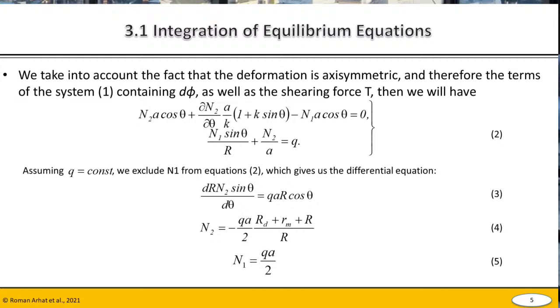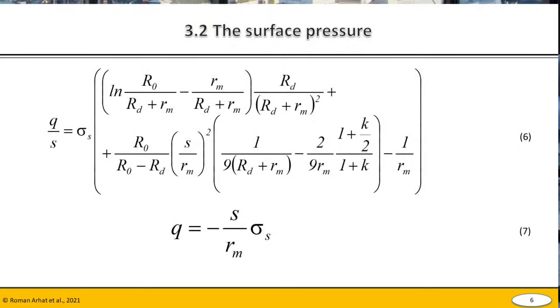Then the surface load is given by equation number 7 at the slide 7. Slide 6, sorry. Slide 6. Thus, an expression has been developed for calculating the surface contact pressure during the drawing down of a cylindrical workpiece, which makes it possible to take friction stresses into account at the rounded radius of the die body, and also to calculate the drawing force. The dependence obtained differs from the existing ones by its simplicity and visibility, and can be used at the preliminary stage of choosing equipment for drawing.